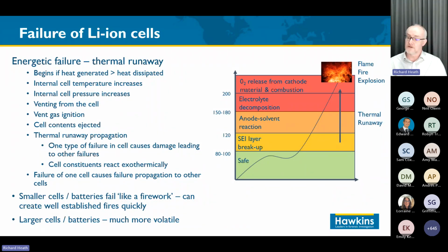And once the temperature goes above that, there are a number of different reactions and breakdown mechanisms that can occur within the cell. And these lead to parts of the cell and constituents that would normally be kept separate coming together. They can react with each other exothermically, and other reactions also produce heat. So you get this problem that once the cell reaches a certain internal temperature, you get a breakdown process that gradually continues to increase the temperature, and eventually the pressure and temperature in the cell increase to the level that